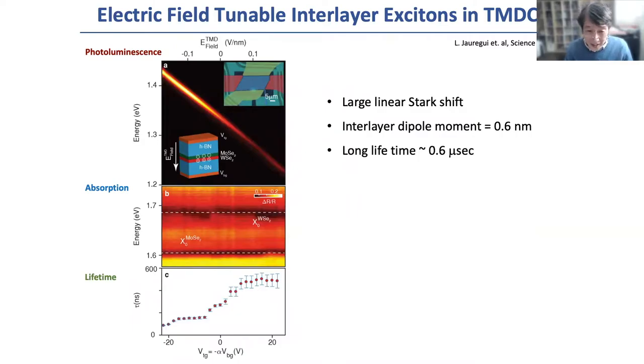That's good. But the more exciting part is their lifetime. Their lifetime is, first of all, something like 200 nanoseconds to start with. It's not bad. But when I apply more electric field, such that the electron-hole separation becomes a little bit longer, then the lifetime quickly extends quite a bit, say half a microsecond, and even approaching a microsecond of lifetime is possible.